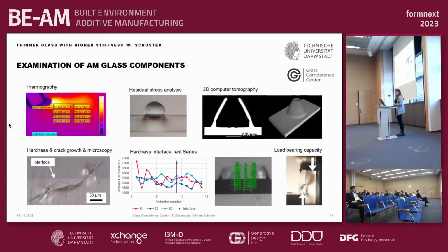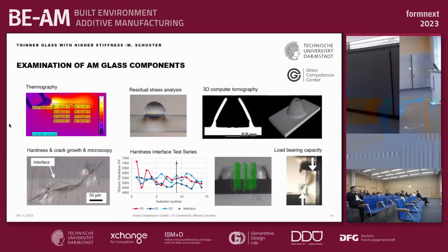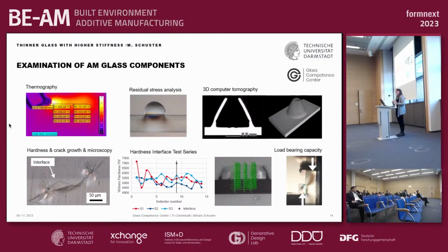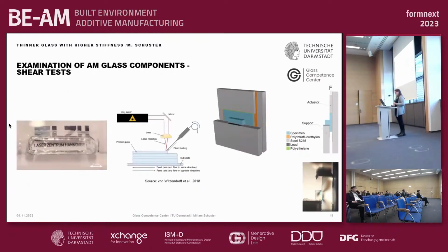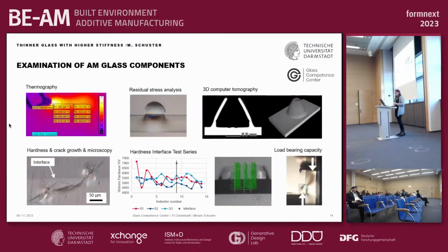Here I want to show some examinations that can be done at different levels of the AM process. In the first picture, we see a thermographic picture. So we use a thermographic camera in order to monitor the temperature during the printing process. When we finish the printing process, we can use photoelastic measurements in order to check the residual stresses in our printed component. So that's here the second picture. Then we can use CT scans in order to create some 3D models and to check whether there are some density differences in our component or if there are some holes or other imperfections.